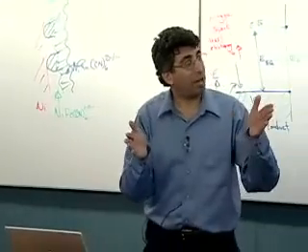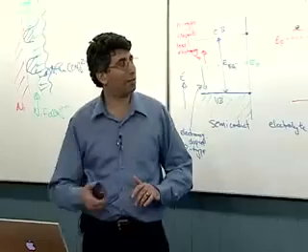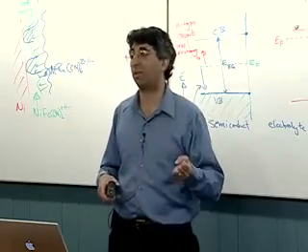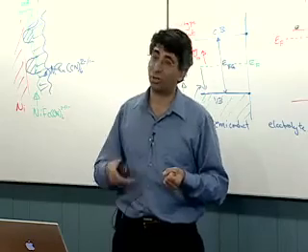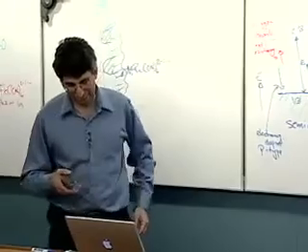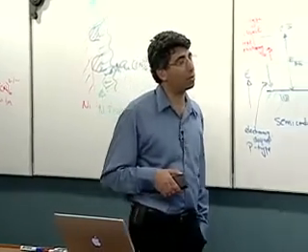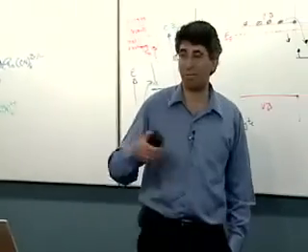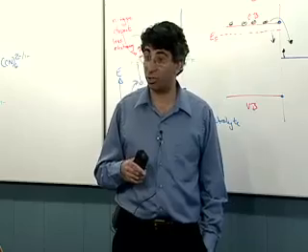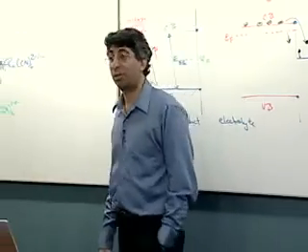On the other hand, if you go to a smaller band gap semiconductor, such as the gallium phosphide here, you start to run into problems where the semiconductor photodecomposes. And so you're limited in intensity, but even that will eventually become problematic. And so one has to come up with chemical schemes, if you will, that shut off the rate constants for photodecomposition while allowing the useful chemistry, such as hydrogen evolution, to continue.